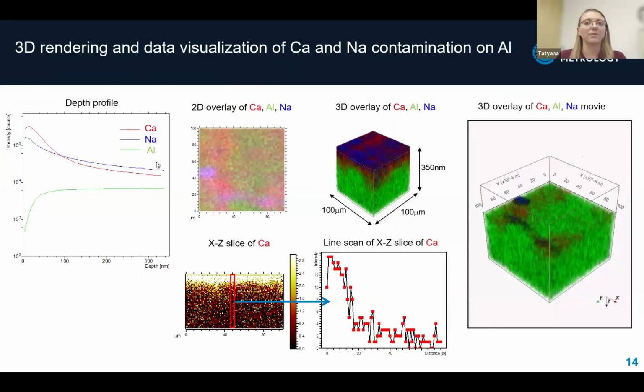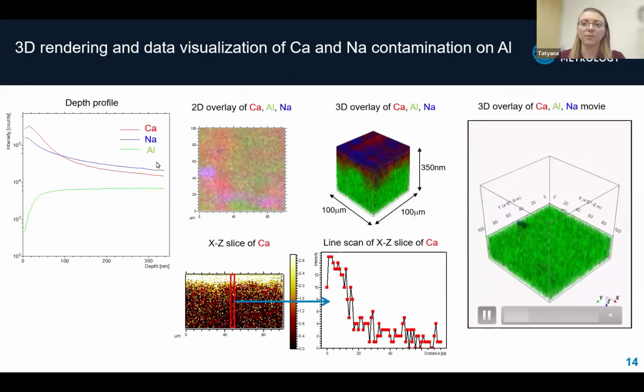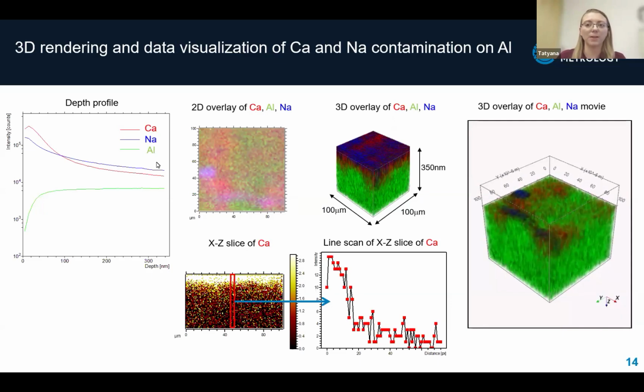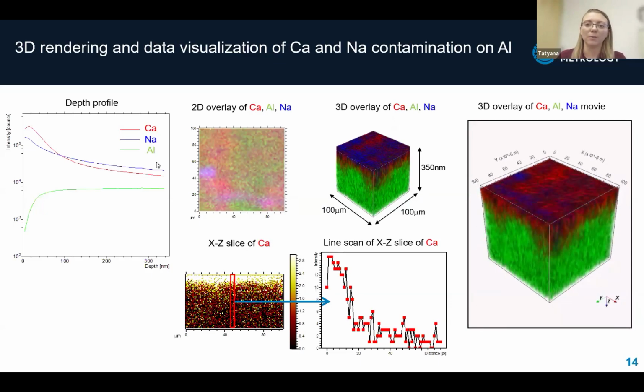In this example, we use time-of-flight SIMS to visualize calcium and sodium contamination on aluminum surface and demonstrate the technique's visualization capabilities. On the left, we see a depth profile, which tracks the signal of calcium, sodium, and aluminum ions as we go deeper into the sample. For 2D visualization, we use a color-coded overlay map, red for calcium, green for aluminum, and blue for sodium. This shows how these elements are spread across the surface.